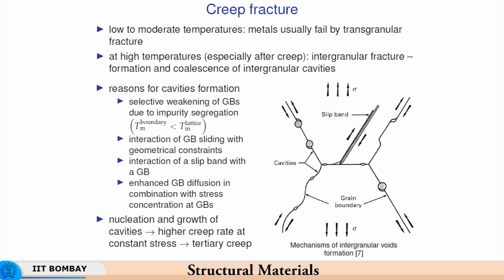As the temperature increases, the grain boundaries become weaker and weaker, and as the grain boundaries become weaker, the deformation tends to get concentrated more in the grain boundaries, and therefore, the strain related activity inside the grain continuously diminishes, and that is the reason why there is a selective deformation or selective weakening of the grain boundaries due to impurity segregation also, because now the impurities would segregate to the grain boundaries because the diffusivity is high at those temperatures, and grain boundary is essentially a region of disorder where the impurities can fit in very easily, and they can diffuse through the grain boundary as well. So, you have impurity segregation.